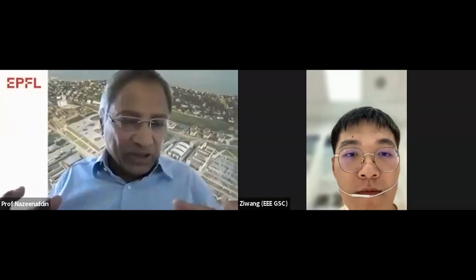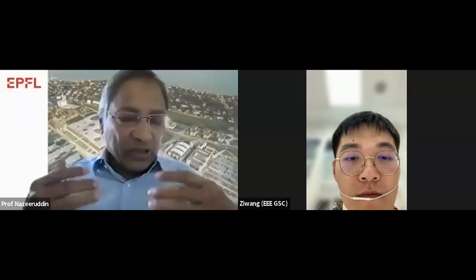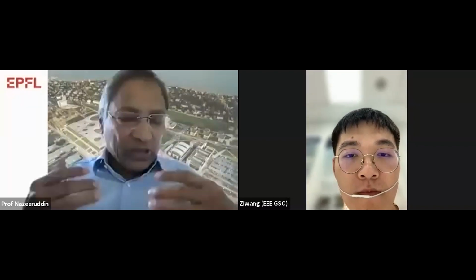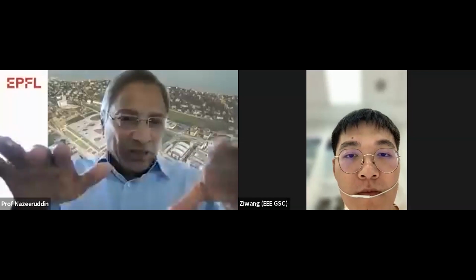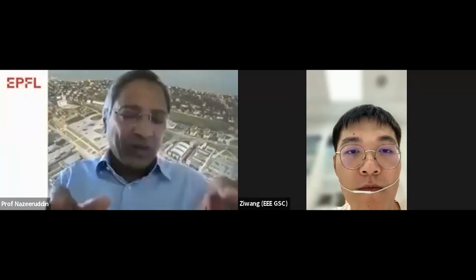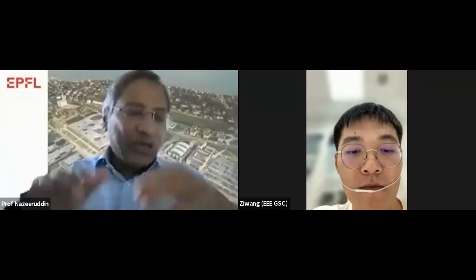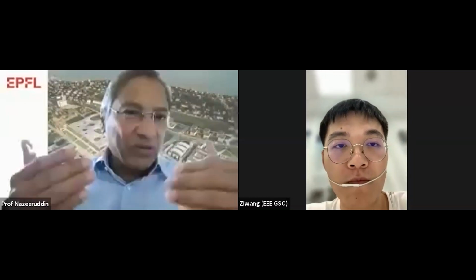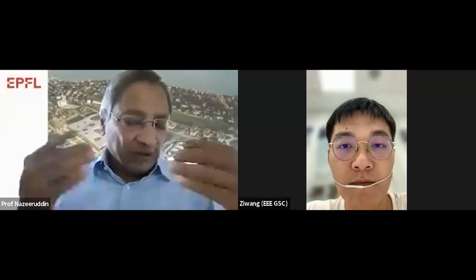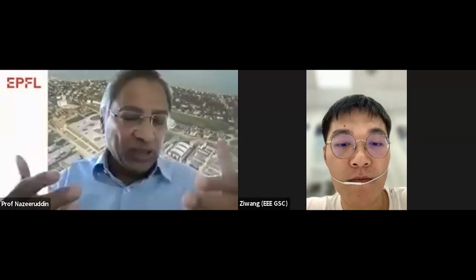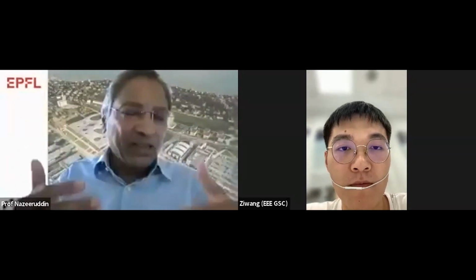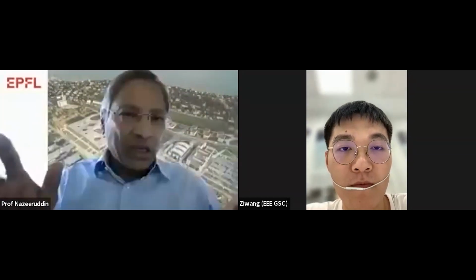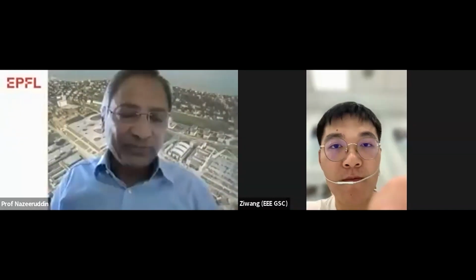So they decompose. In order to prevent this, we try to deposit hydrophobic interlayers on top of the perovskite. The purpose of this interlayer interface engineering is twofold. One, passivation of the defects. The second is protecting the perovskite by a hydrophobic blanket on top of the three-dimensional perovskite.